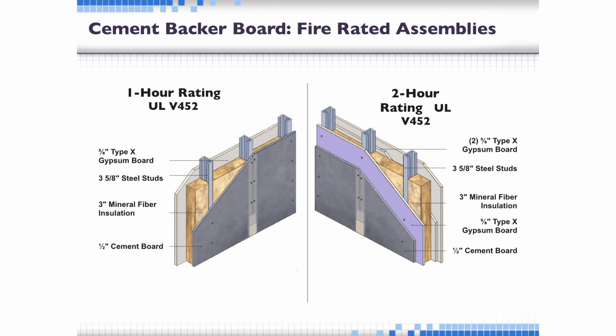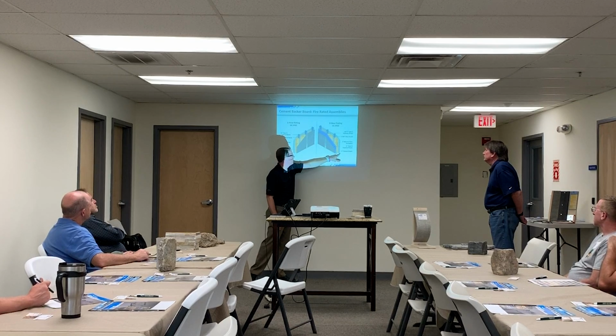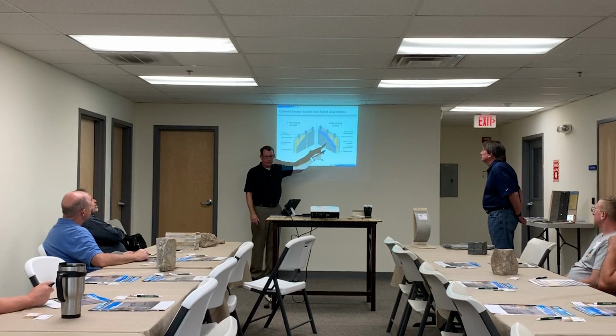If you have a 1/2-inch drywall, we have the mineral wool, metal studs, and then the 5/8 type X for a 1 hour wall. When you do commercial work 2 hour walls, we just have to double up the 5/8 X on one side. We use the 5/8 X mold and moisture resistant board now. That's the purple that is kind of indicating that, with the 1/2-inch cement board, and we stick our tile to that.